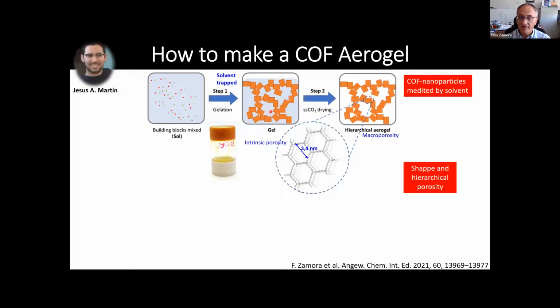And for that, what we did is we exchanged the solvent, the acetic acid, with ethanol, okay? And then we dried the gel using supercritical CO2. In that way, we pass from gel to aerogels, okay? And the idea was to produce a material having two porosities: the intrinsic porosity of the structure of the COF plus the macro porosity of the gel, okay?